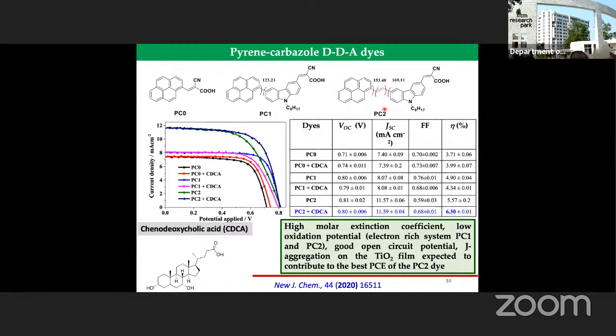That's what we were seeing in this molecule. At the time, we were not sure why this is happening with this molecule, why there is a decrease in performance. Generally, literature says with the CDCA, performance goes up, but it is not. But here in this case, when you include CDCA, the dye loading comes down also heavily in all the cases. That is one reason why less conversion happens.